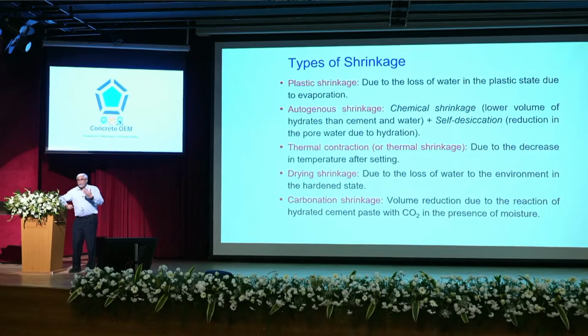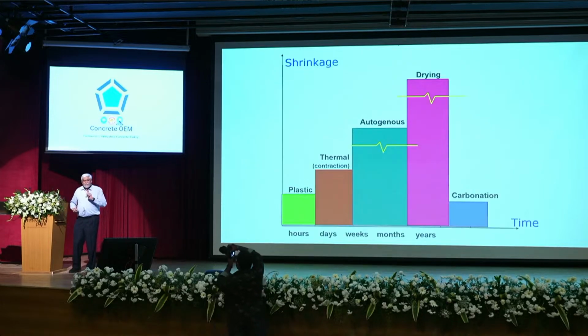Carbonation shrinkage, again, will become less and less important when we go to higher quality concrete. Anyway, this occurs over a large period of time. So it's very important, and this is important for consultants also. If you are a consultant and somebody calls you and says, my structure is cracked, the first thing you should ask is, when did you see the crack?